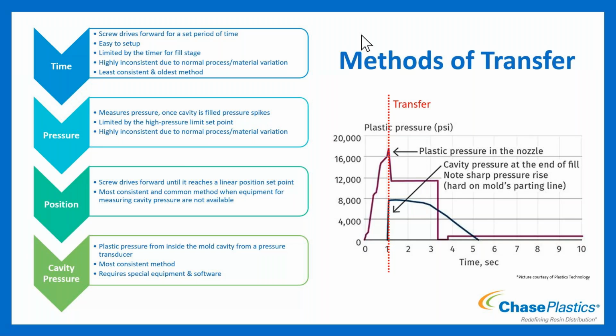So another way we can do this then, a little bit better, is by giving some feedback and doing it by pressure. Once the screw reaches a set pressure, then we're going to transfer over to pressure control. Again, though, this is not directly tied to volume, but tied to pressure. So if our melt temperature changes a little bit, if our molecular weight changes a little bit, our transfer is now changing. And we are changing the volume of material that we're putting into the cavity.